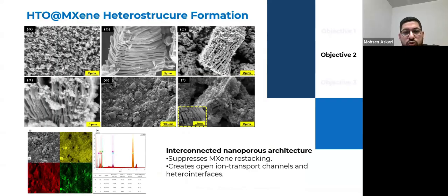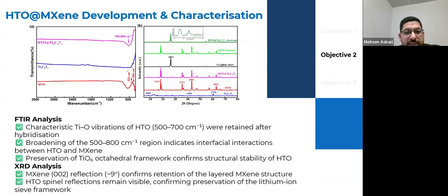The SEM image shows, like the previous chapter, the HTO anchored on top of the MXene sheets and between the layers. An interconnected nanoporous architecture has been formed that suppressed the MXene restacking and created open ion transport channels and hetero interfaces. The characteristic Ti-O vibration of the HTO in FTIR analysis was retained after hybridization, broadening of the 500 to 800 region indicates the interfacial interaction between HTO and MXene, and preservation of the TiO6 octahedral framework confirmed the structural stability of the HTO.